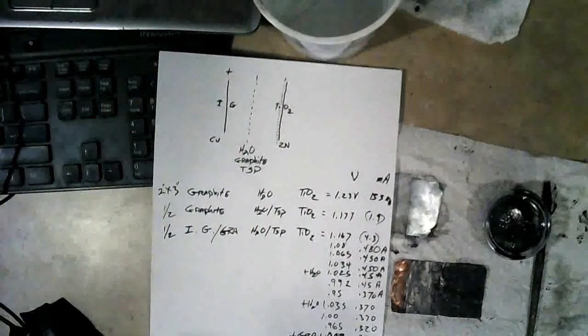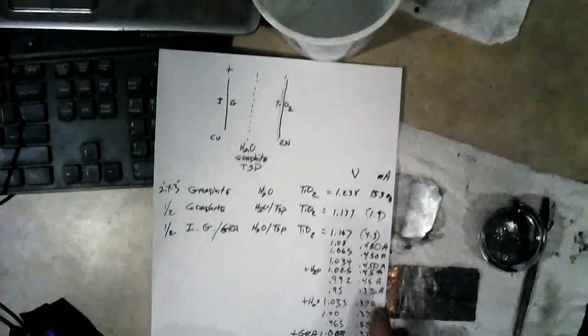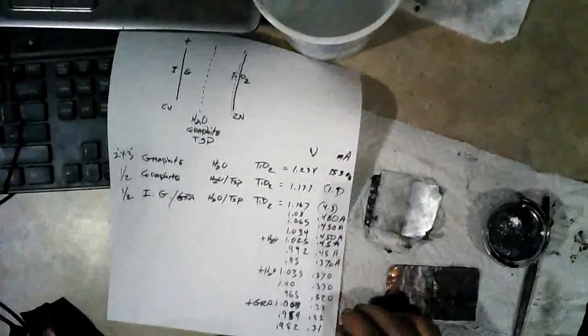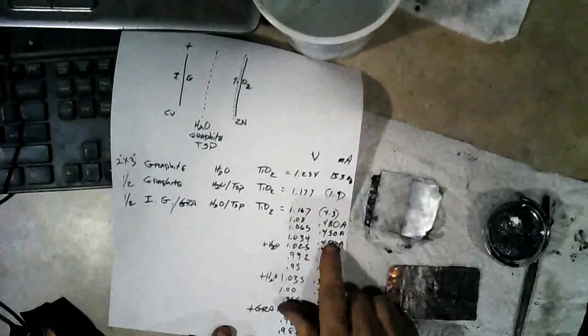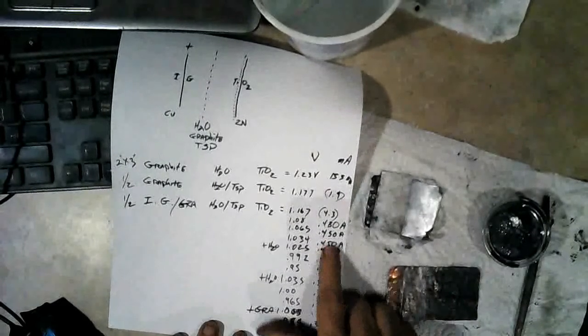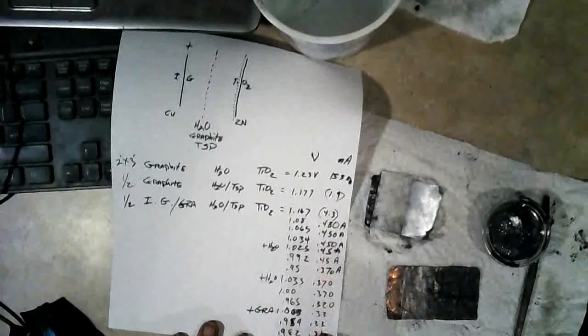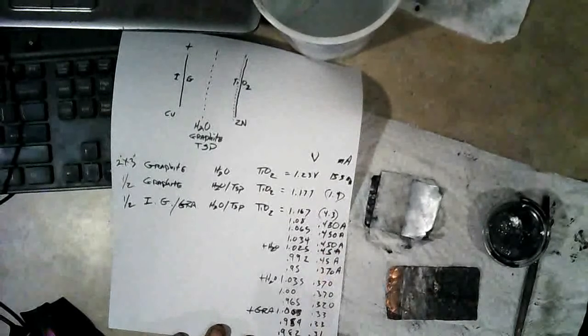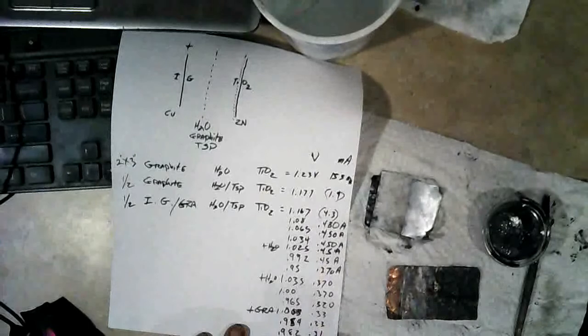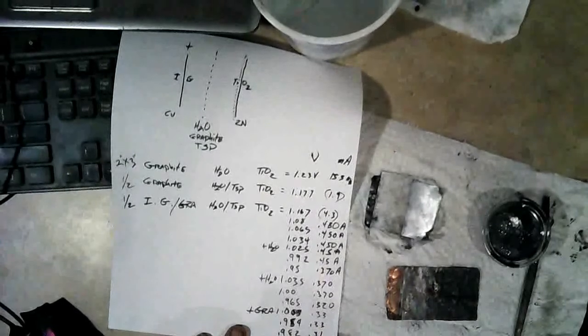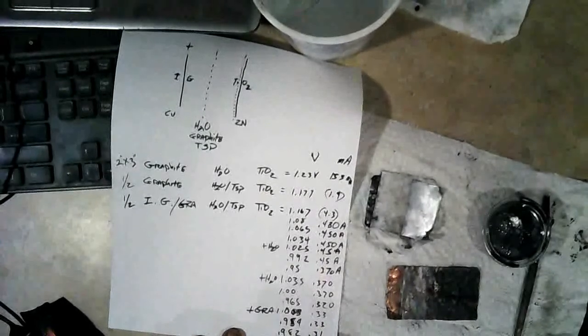Alright, I'm back with a wrap up here. I cycled this cell a total of 13 times. Its peak amperage was 450 milliamps near the beginning, and it slowly dropped off to 310 milliamps at the 13th cycle.